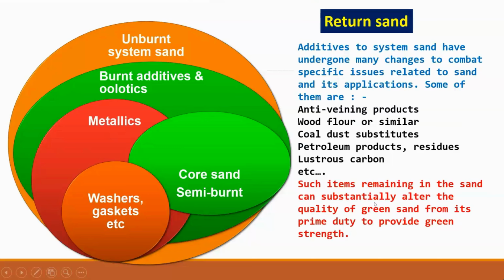Such items remaining in the sand can substantially alter the quality of green sand from its prime duty to provide green strength. Now, why is it? Because these products are very small in size, much smaller than the sand grains. So when these products are added, they have a surface area which is very high compared to the sand itself. And they are water absorbent, except for perhaps the lustrous carbon. Everything else is going to absorb some moisture. So when you are adding water to the returned sand for reconditioning, some of the water will be absorbed by these and then deprive the actual bentonite from absorbing the water for its strength purposes.